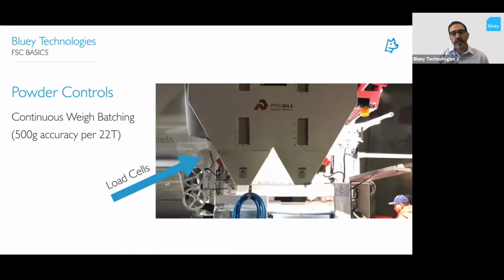And what that means is that on your powder bins, you have load cells, which are continuously weigh batching the powder as it's delivered from the powder bin. And it gives you really high accuracy on that powder delivery, which combined with electronic controls over your water delivery gives you an extremely accurate water cement ratio all the way through your pour. So you know you're going to get the strengths you want, you know you're going to get the consistency you want all the way through the delivery of that product.